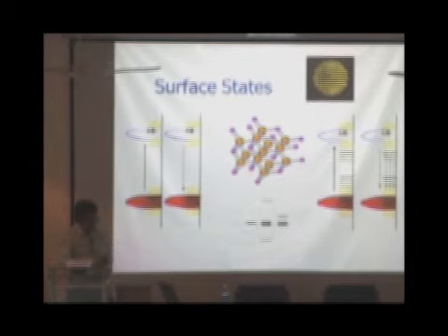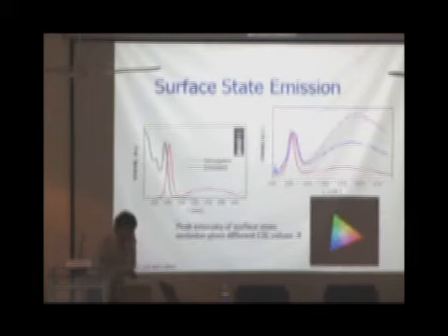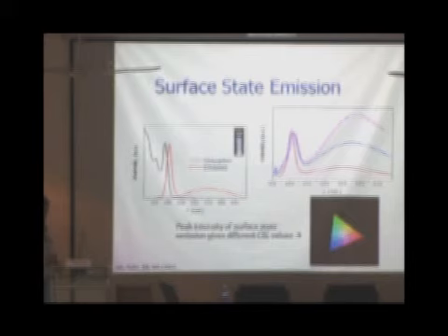So you have a sharp ultraviolet blue peak, and when these states come in, they will automatically be lesser in energy, so they'll take care of the green, yellow, and red regions. And if I can tune that emission, I could get very good white light emitting particles over here. And by doing some good chemistry over there, you can actually tune the surface. But you cannot tune the intensities so easily. They just happen to come.